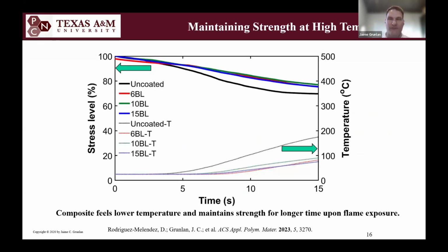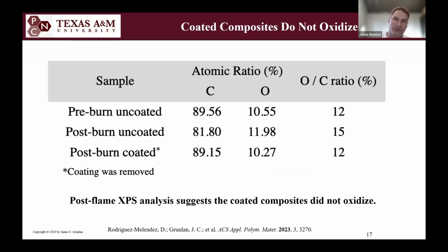And so this is the stress. This is where we're measuring stress as a function of time with a torch on a composite. And of course, the uncoated, and then 6 bilayer, 10 bilayer, 15 bilayer means how many bilayers of that nano brick wall we put onto the composite. And in any event, you can see that the stress level that the composite can hold reduces much faster without the coating. So we're buying time with this relatively inexpensive clay nano brick wall coating.